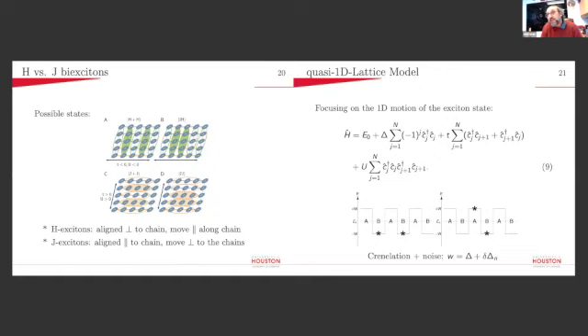In that, H-excitons, which Carlos gave a great overview of, are more or less aligned perpendicular to the chain. They stack like this, but if you think about it, they must move parallel along the chain. Likewise, J-excitons are aligned parallel to the chains, but move perpendicular to the chains. That tells you right there that the hopping integral in the different directions for an exciton, taking the exciton as the quasi-particle, is different depending on whether you're more H-like or more J-like in your behavior.